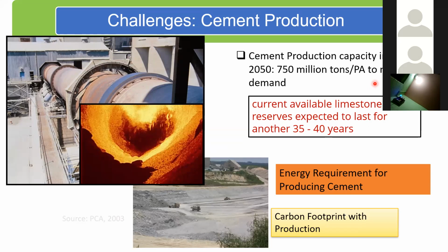Cement also, because we need such large cement. The estimated requirement of cement is 750 million tons per annum in 2050. It is so large, in fact, the projected demand, that it is raising concerns. The reserves are projected to last 35 to 40 years. It's the good grade limestone that goes into making cement. Energy requirement for producing cement is high. It is an energy intensive material. So we have to look for alternate sources of energy to sustain the production of cement. And of course, the large carbon footprint. Cement has a very large carbon footprint.